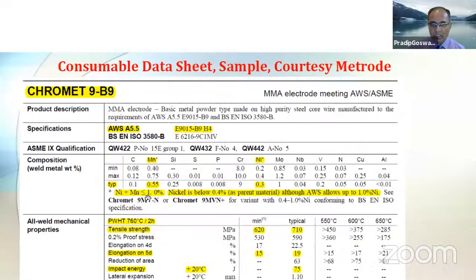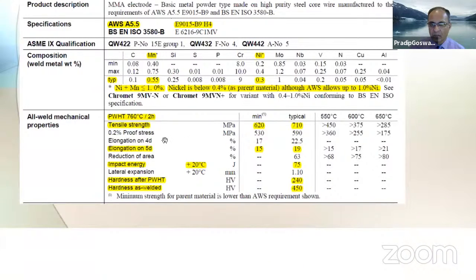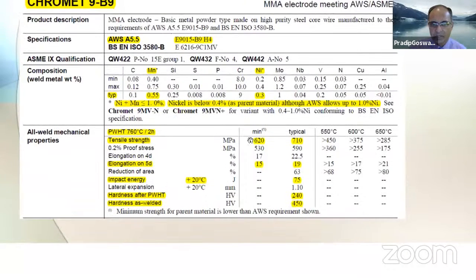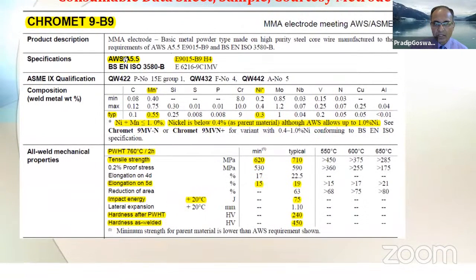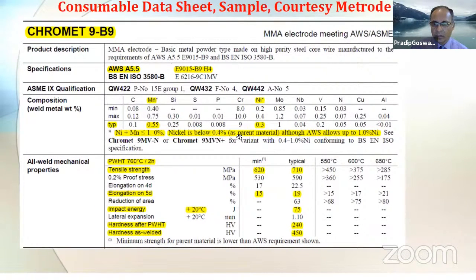So in the same note, these are the continuation of the mechanical properties as well as different compositions. So you see here that Metrode can give you the same consumable, the grade 91 consumable, in less than 1% manganese plus nickel content also.